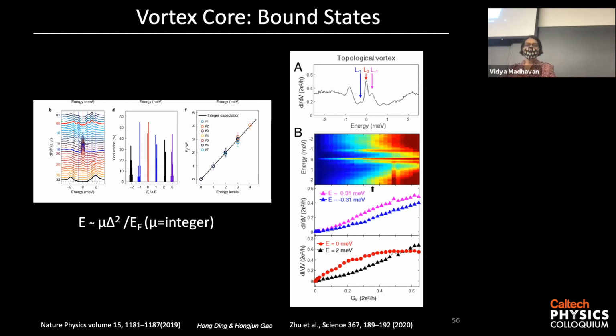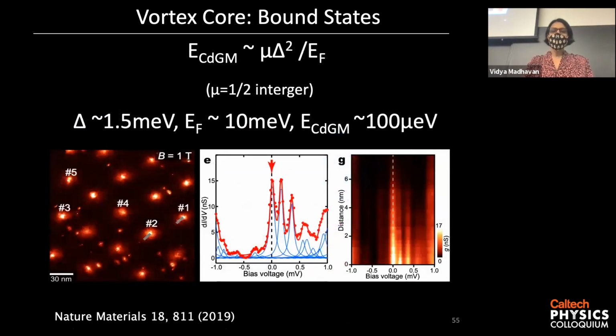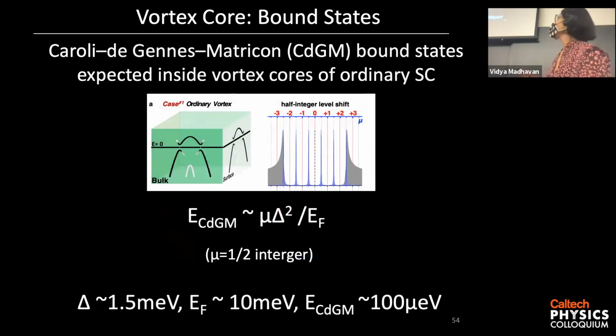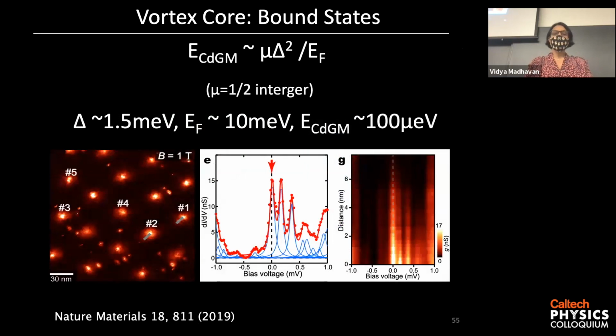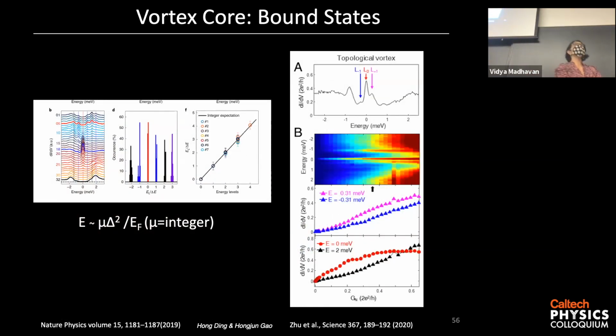The second interesting thing that was found with these zero bias peaks is the following. The Caroli-de Gennes states, actually, you can have many of them, their energy spacing, right? Their energy spacing goes as half integer times delta squared over E_F. So that's a very definite prediction. Whereas what you can show is that even for Majorana fermions, you can have many such bound states, but those energy spacings go as integer times delta squared over E_F.